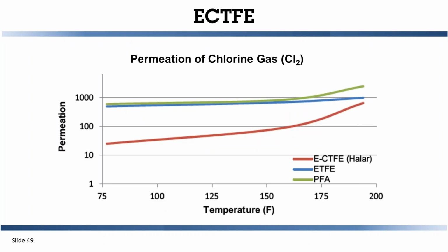The main reason ECTFE has great chemical resistance is the permeability of it is very, very low. A standard test performed on ECTFE is permeation of chlorine gas, which is Cl2. Basically, you inject Cl2 on the inside of the pipe and then see how much it transmits into the wall of that piping system.